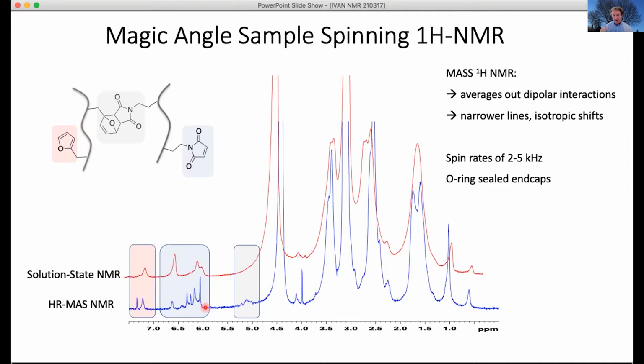Most of the polymer is mobile, but the magic angle spinning adds this end-over-end tumbling that we need on the NMR timescale. The only difficulties are the spin rates are very, very slow for magic angle spinning. We need O-ring-sealed end caps to prevent leakage of the solvent.